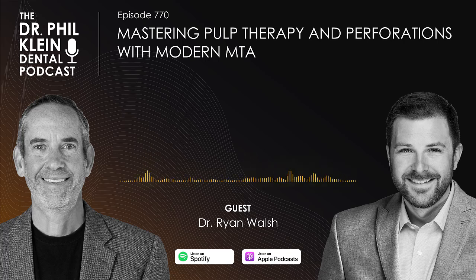Whereas in years past, you just place calcium hydroxide over the pulp and you just really hope for a strong enough irritation reaction, more or less, to stimulate this dentin bridging. Where MTA has this prolonged release of calcium ions and calcium hydroxide, it provides a much more predictable way to do pulp treatment, whether it's vital pulp therapy, like you had mentioned before, perf repairs, things like that, to stimulate that hard tissue formation in a much more predictable manner. And it forms a really tight seal between the restorative material, the MTA, and the dentin or the tooth structure.